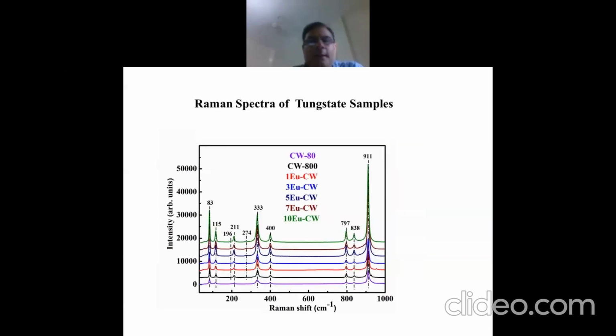And this is the Raman spectra of calcium tungstate samples doped with europium. All these peaks are due to the W-oxygen bond vibrations. We don't see any peak due to europium-oxygen bond vibrations, probably because the europium oxide concentration is small. Its maximum concentration is about 10 mole %. And moreover, W-oxygen bond vibrations are much more strongly Raman active than europium-oxygen bond vibrations.